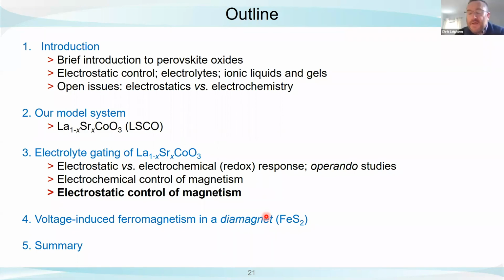Yeah, so we use this side gate, right? And the reason we use the side gate is just for convenience, because we're bringing in X-rays and neutron beams and doing operando experiments. That slows things down by multiple orders of magnitude, because in some cases we have a centimeter between the gate and the channel. So once we've learned how this works with the operando probes, we're taking the side gate away using a top gate. And then we can take the electrolyte thickness down to something like a micron or even less.